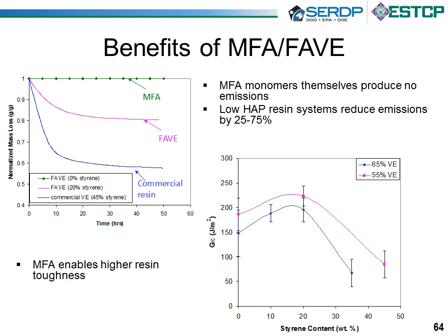So there are various benefits to the methacrylated fatty acids and the fatty acid vinyl ester resins. First, if we look at this plot in the upper left corner, we see basically the mass as a function of time. Basically, what we did was we took a sample of our resin and we put it in an oven at a particular temperature and looked at the mass loss as a function of time, and we found that the methacrylated fatty acids themselves are non-volatile. As opposed to the commercial vinyl ester resin shown in blue, which is very volatile. It will lose all its styrene mass as a function of time, and it loses it at a very rapid rate initially. Whereas the fatty acid vinyl ester resin shown in pink loses only, again, its styrene content and loses it at a lower rate. So that's a significant advantage of these fatty acid vinyl ester resins.